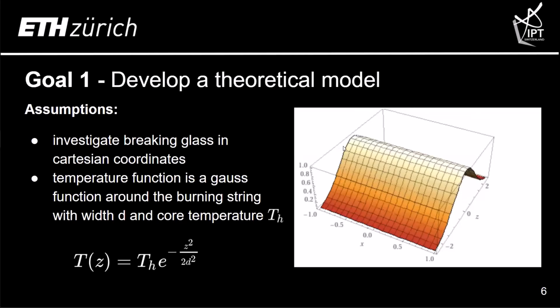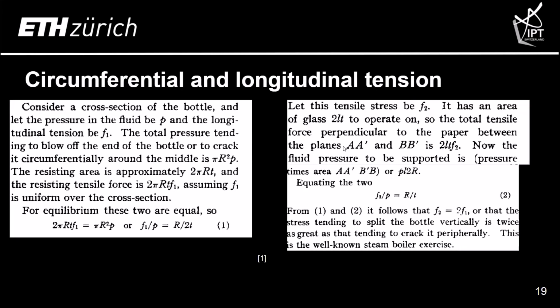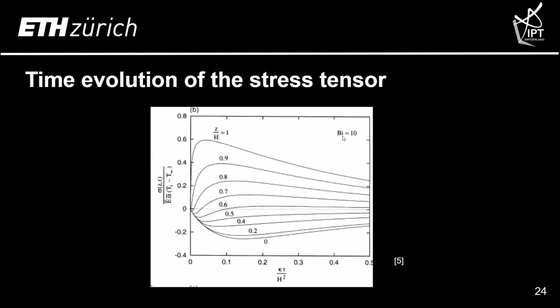Exactly, here you can see the time evolution of the stress tensor. It's from an experiment actually from your university in Cambridge. On the left axis, you see the tensile strength denoted in a dimensionless way. And here you have the time evolution multiplied with the thermal conductivity divided by the area of your glass. And those different parameters, Z divided by H is a measure for the position where you are, so how far you are away from the source of heat.